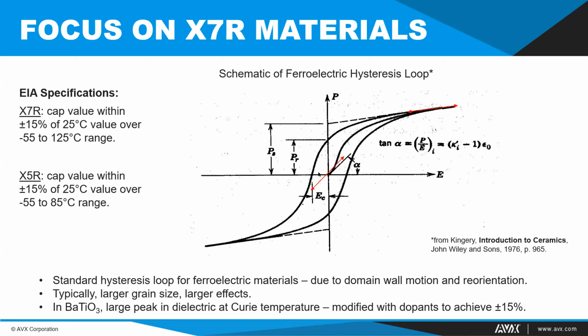So you can see one red arrow has a certain slope, a relatively high slope at low bias fields, but up at higher bias fields, it gets a relatively low slope at that point. And so having a higher slope down here, and a low slope up there, means that the dielectric constant actually falls over that range too. And so as we start thinking of devices for higher voltages, we have to understand that there will be some roll-off in the properties.